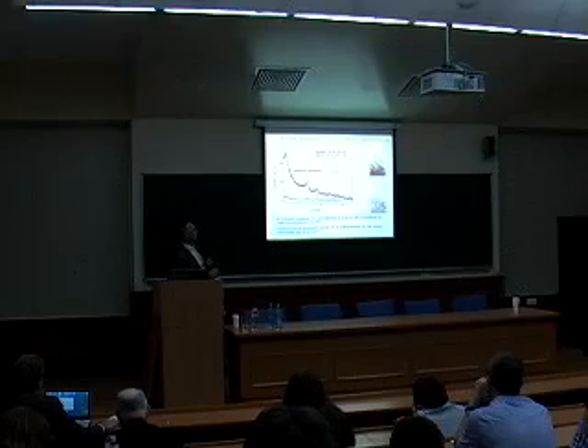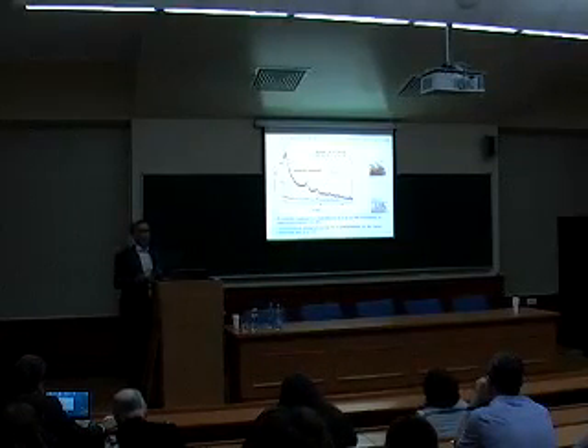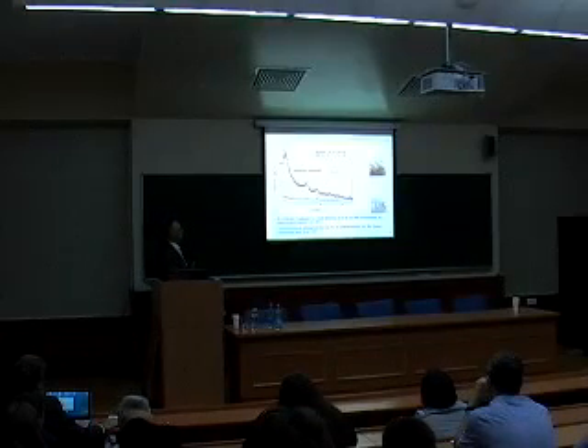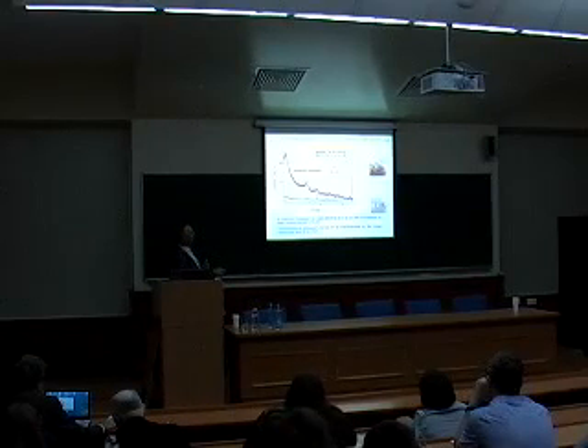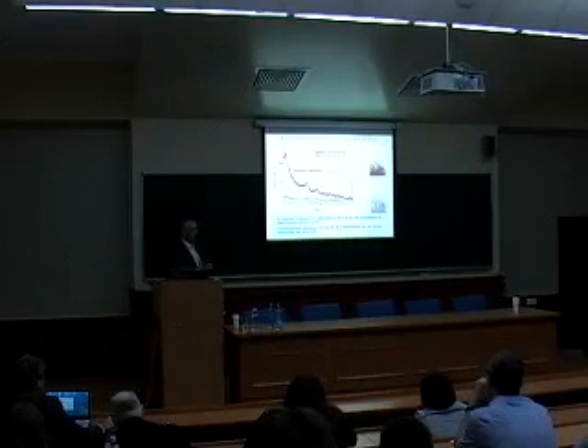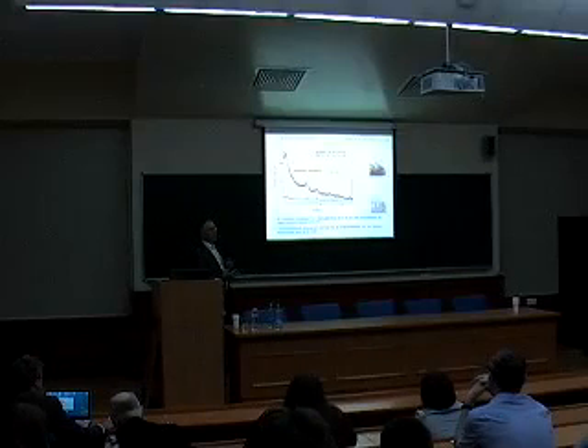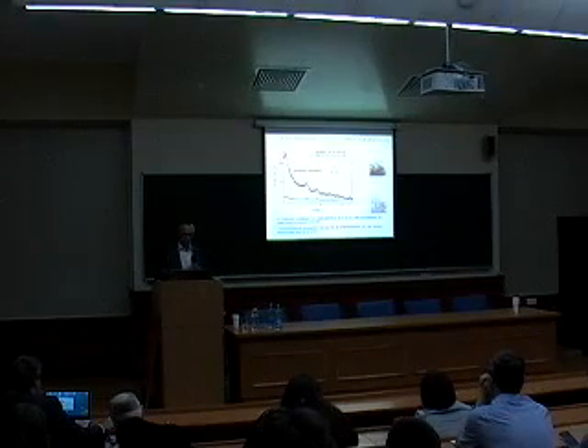You see broadening on the tails of diffraction peaks, and the nanoscale origin of such material can also be visible by naked eye from these images. You see the powder of the smallest silicon nanoparticles is brownish or even red, while the larger particles are gray, similar to bulk material. That's due to what is called the quantum size effect, which changes optical properties due to change of the electronic spectrum of silicon nanocrystals. These powders can be used in order to prepare